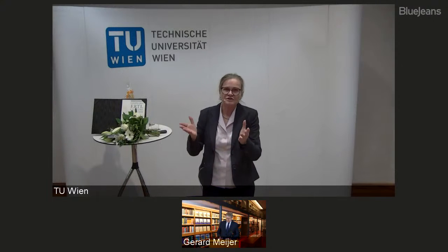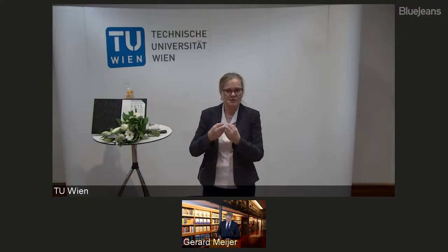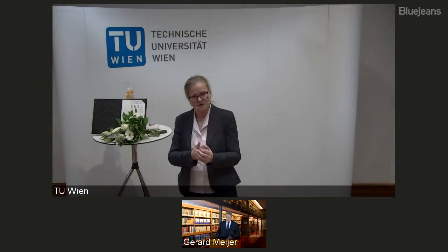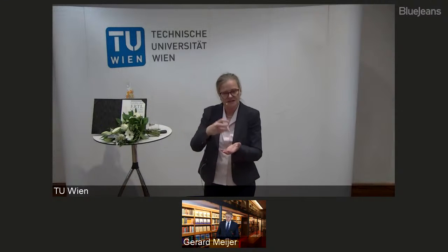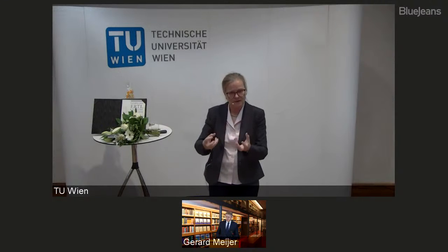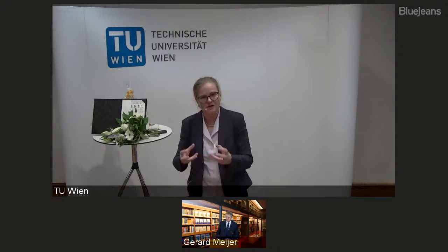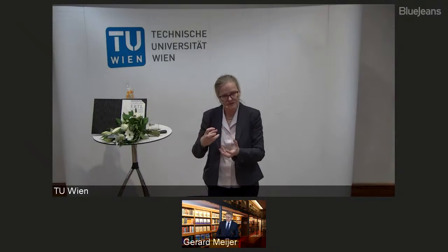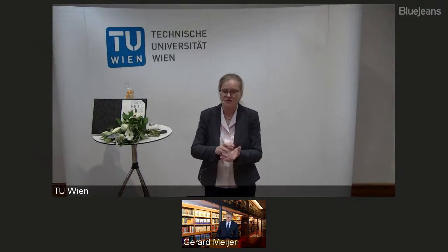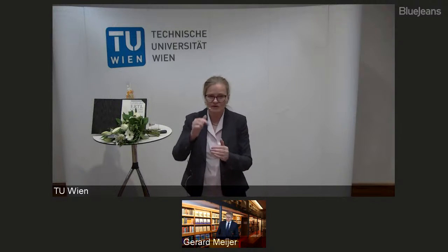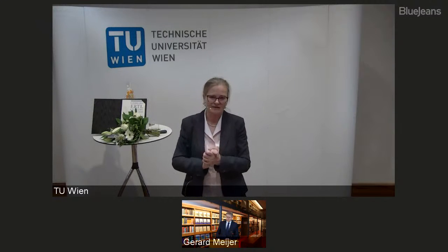In some sense yes, in some sense no, because one uses different molecules also in other cases, like I showed with the zeolites, one really looks at this acidity, so weak adsorption or weak interaction or strong interaction. One probes different gas phase molecules with acidic sites on the surface, just in a very different way than we do it with one single molecule on the tip.